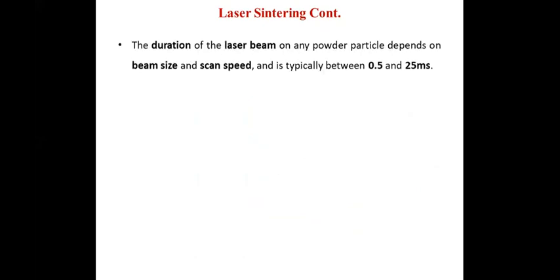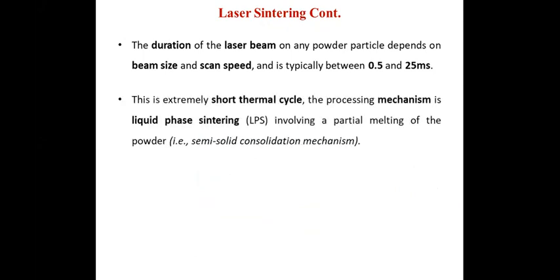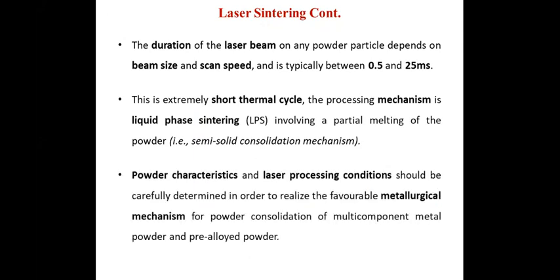The duration of the laser beam on any powder particle depends on the laser beam size and scan speed, and typically it varies between 0.5 and 25 milliseconds. This is an extremely short thermal cycle. The processing mechanism is liquid phase sintering, involving a partial melting of the powder, which is called a semi-solid consolidation mechanism. The powder characteristics and laser processing conditions should be carefully determined in order to realize a favorable metallurgical mechanism for powder consolidation of multi-component metal powder and pre-alloyed powders.